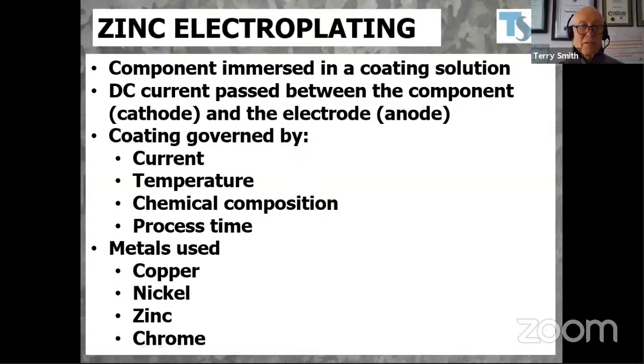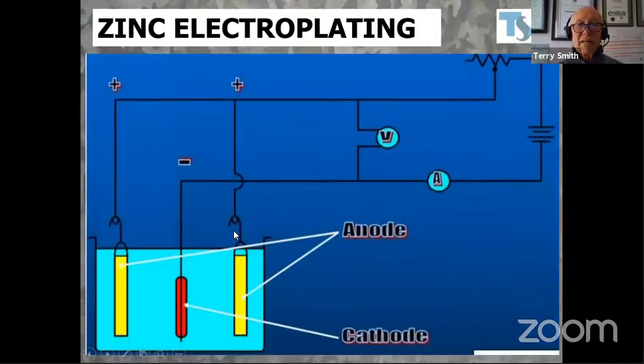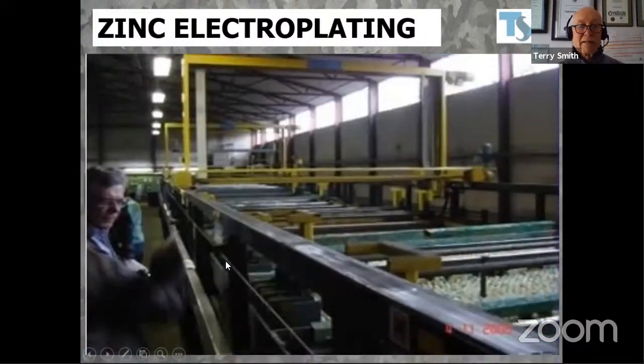Metals that can be used: copper, nickel, zinc, and chromium, and we're going to talk a bit about zinc. You can see a typical zinc electroplating process, where you have the anode and a cathode, an electrolyte which contains a zinc cyanide or zinc chloride, and once the circuit is closed, the coating solution plates onto the cathode and the electroplated item happens.